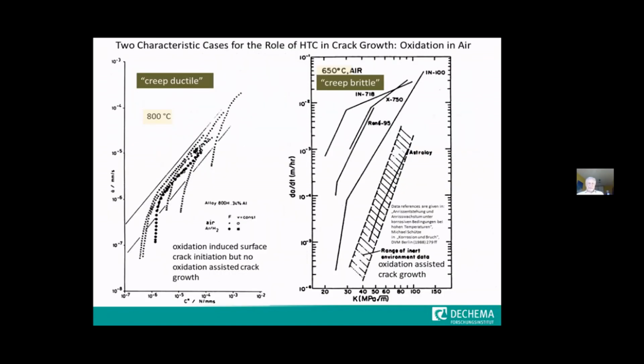And now here, 2 examples of what will be coming out from these measurements. You should ignore this part of the curve. This is due to the measurement technique. Interesting are these lines here. This is a plot where a fracture mechanics parameter, the high temperature fracture mechanics parameter C star, which is being used for creep ductile materials, relates the crack growth rate to the C star value, and then you get such a scatter band. In this case, the question was whether there's an influence of the oxidation on the crack growth rate. We had the inert environment compared to air, but you can see there's no difference. So the crack growth rate itself is not affected by the oxidation, but as we'd seen before, the crack initiation can be assisted by the formation of grain boundary oxides in the subsurface region.